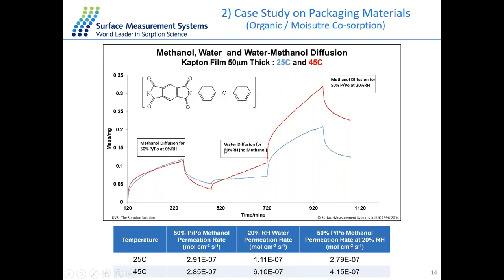Well, on the second stage, the water only stage, the plots are quite different from each other. And the value at 45 degrees is almost 5 times larger than at 25 degrees. So that means the water molecule has a faster diffusion rate at higher temperature, because higher temperature encourages more molecular mobility, which results in higher diffusion for the water molecules.